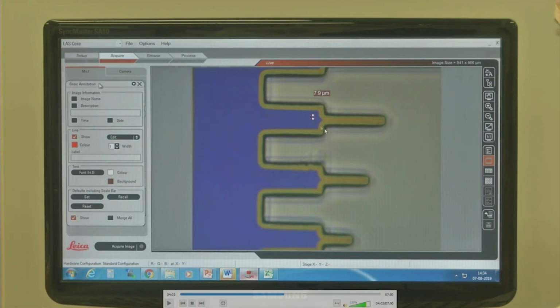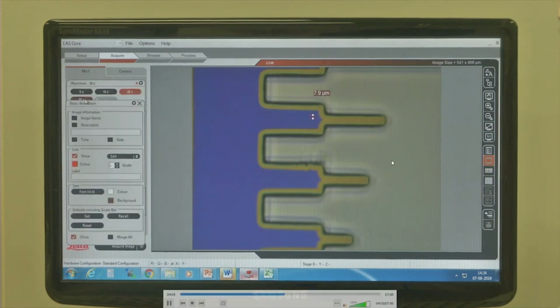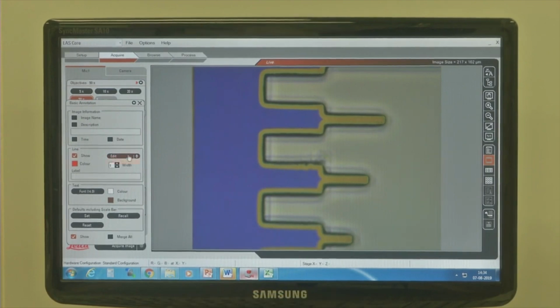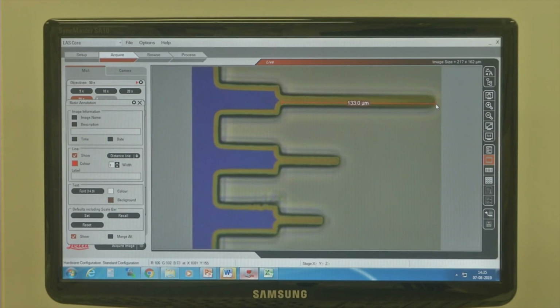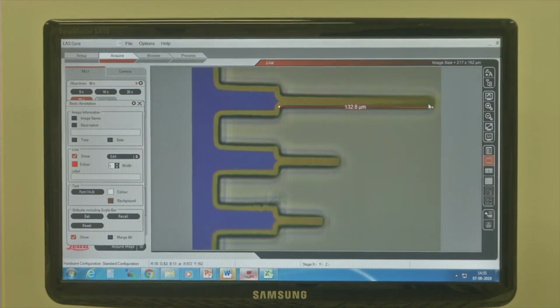What you see here is a very fine isotropic feature, right? Normally in an isotropic etch you don't get sharp corners, so the corner will be made into a curve like this. That is what we see here as well. We are redoing the measurement. The length of the cantilever is also measured here, which is 132.8 micrometers in this case.